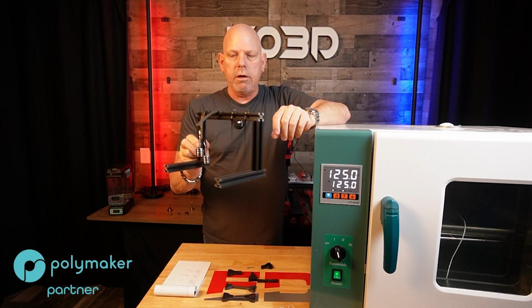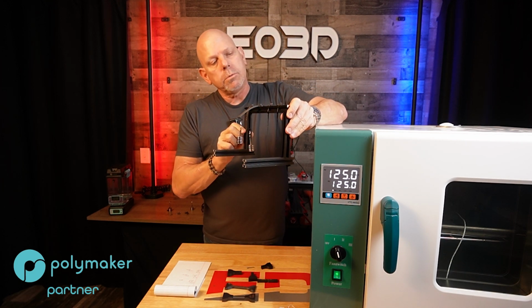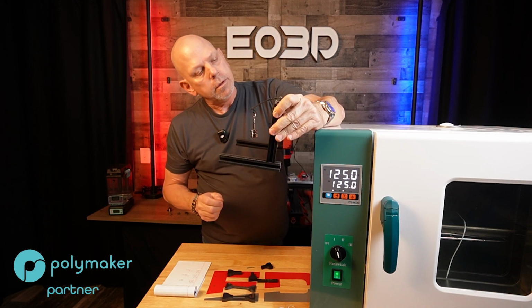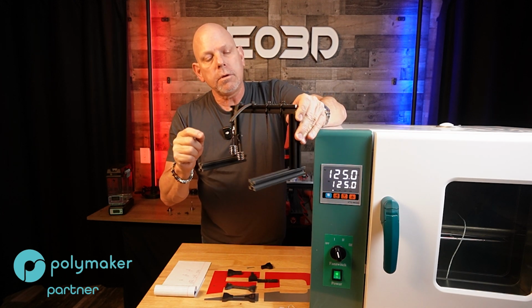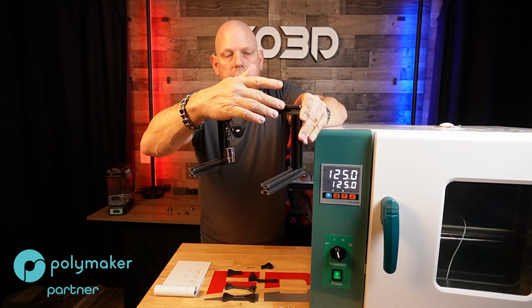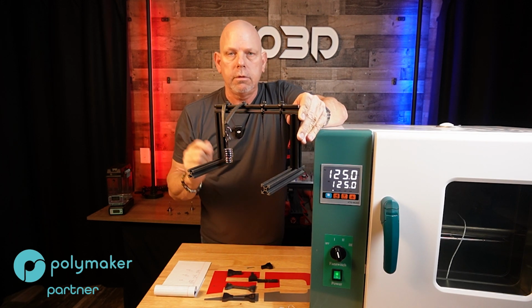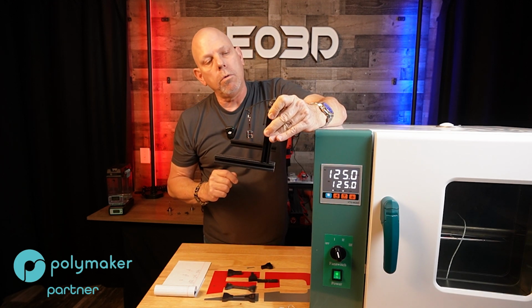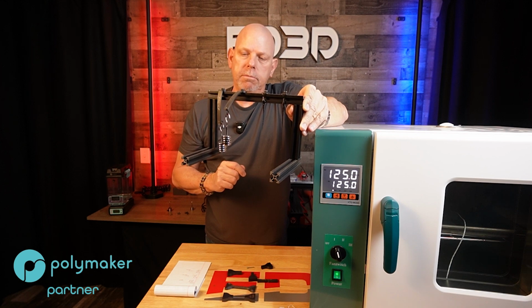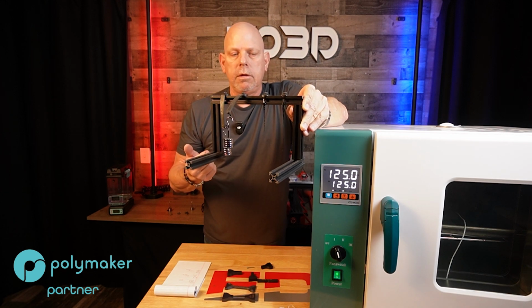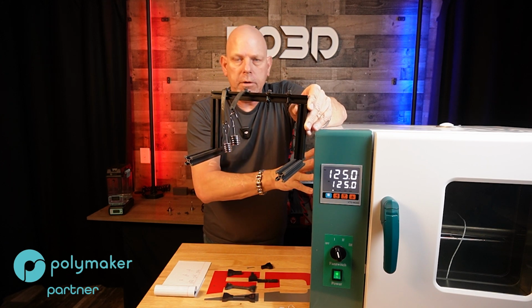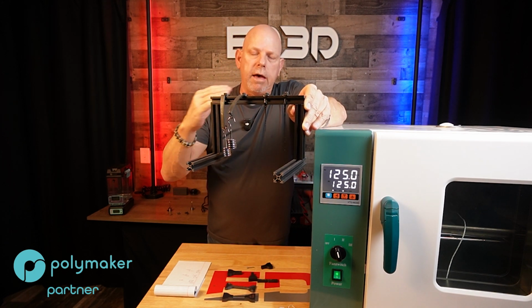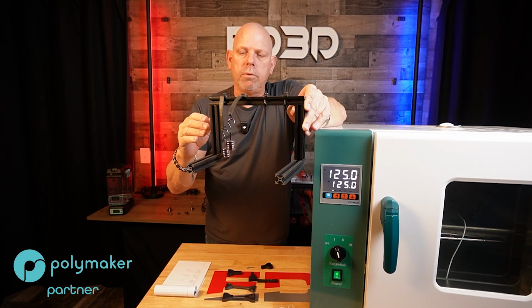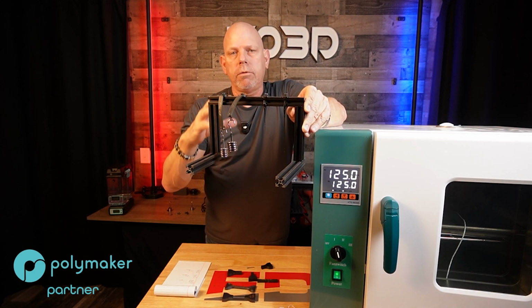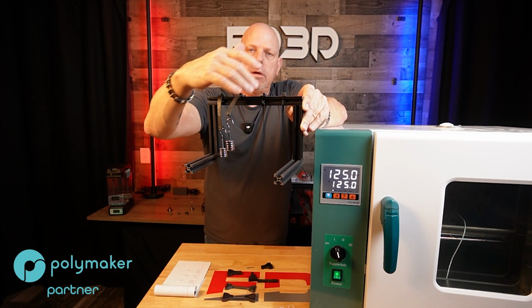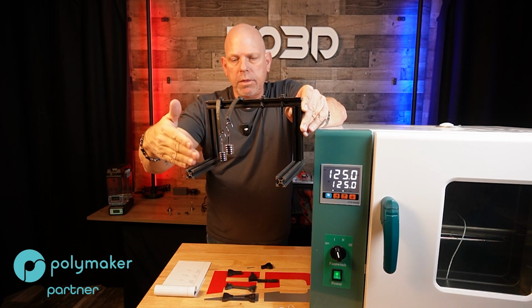Which, if you've seen the video on this, this was a heat test, and this is PA6 carbon fiber, and this over here that turned into liquid was PA12. So there's a video out there about this, but this is one of the tests I came up with. I print these parts out, I put them here in this oven, and I start in 5 and 10 degree increments, depending on how high a temperature we're going, and I let it soak for an hour, and then increase the temperature, let it soak for an hour, and I document each hour as to where these are sagging, when they start sagging.